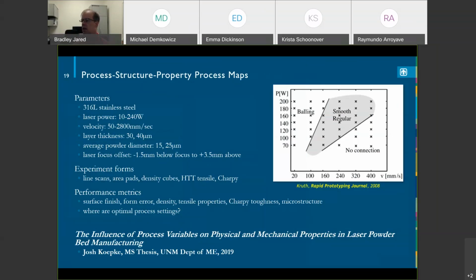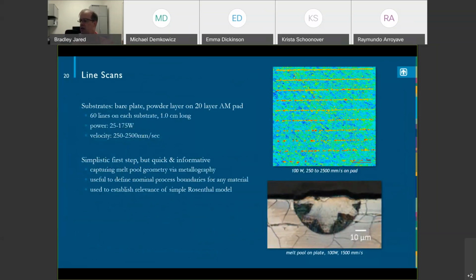First thing, we started off with simple line scans. These are actually super easy to do. The challenge here is actually characterization. This scan is actually just lines on a solid plate or on a buildup of powder, or what we call a pad. The run itself takes a few seconds, right? You hit go and you blink and it's over. But what we do is we cut these up and characterize these. They give us a really good indication of process settings, of melt pool conditions, of depth and width, whether we're getting lack of fusion or balling or keyholing or stuff like that. So these are really, really effective.